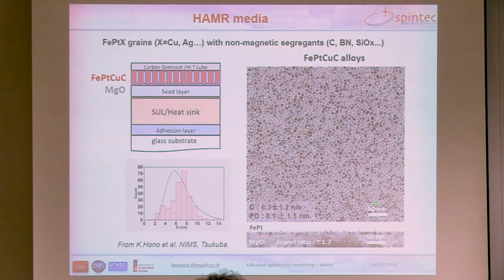So the media actually looks like this. It's a granular media. You see here these grains, and the size of the grains is typically in the range of 6 to 8 nanometers. This is a distribution of grain size. Here we have the magnetic media itself, this iron platinum copper carbon alloy. The carbon is a segregant which diffuses to the grain boundary. Then we have a seed layer here, which is magnesium oxide. And underneath, we have a heat sink. It's a copper-based alloy, which pumps the heat, which will be dissipated here at the top surface of the disc.